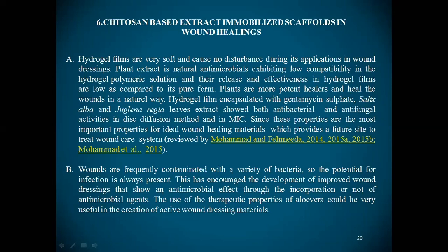By the way, a hydrogel film encapsulated with gentamicin sulfate, Salix alba, and Juglans regia leaves extract showed both antibacterial and antifungal activities in the disc diffusion method and in the minimum inhibitory concentration method.